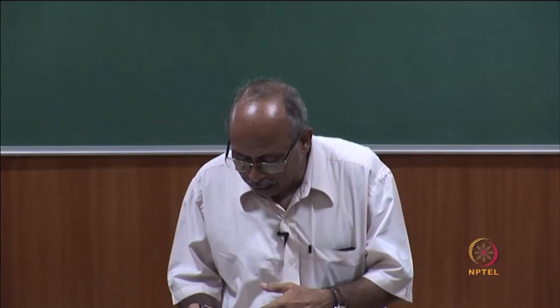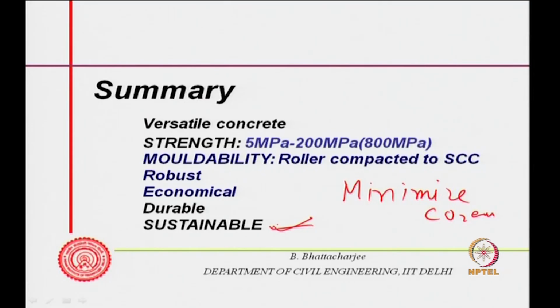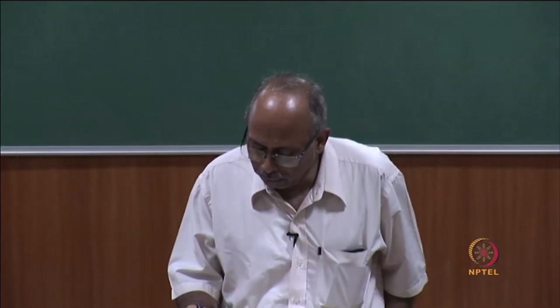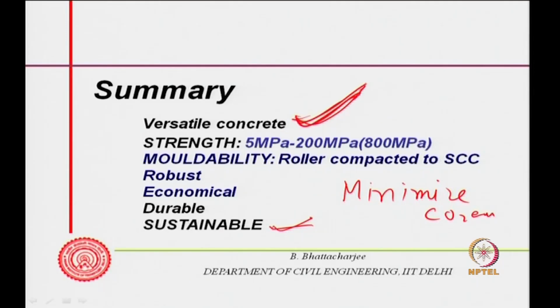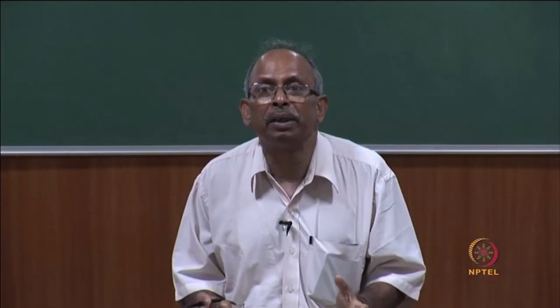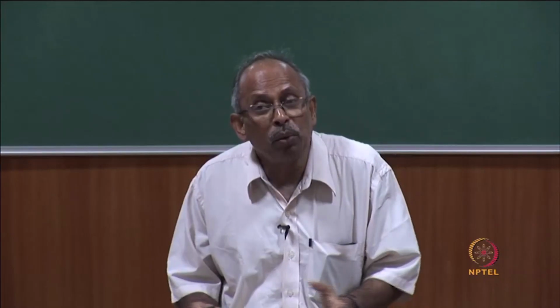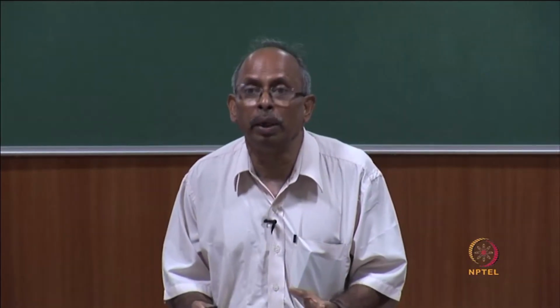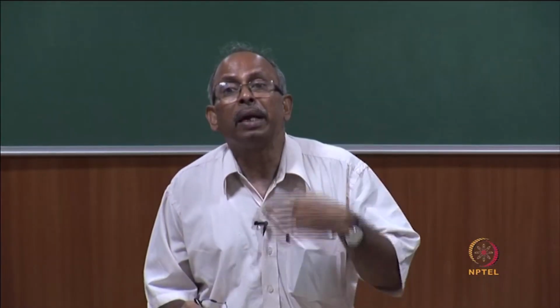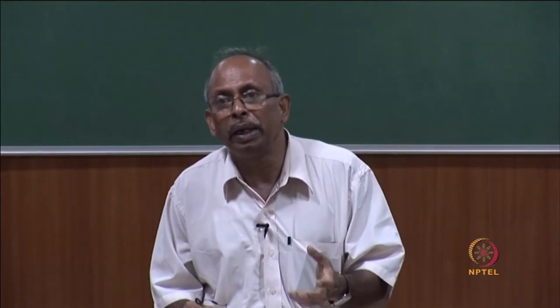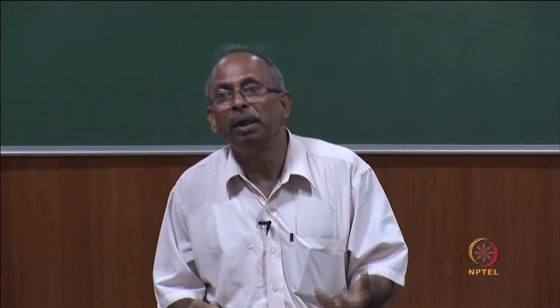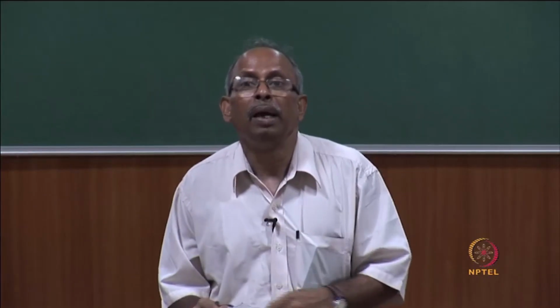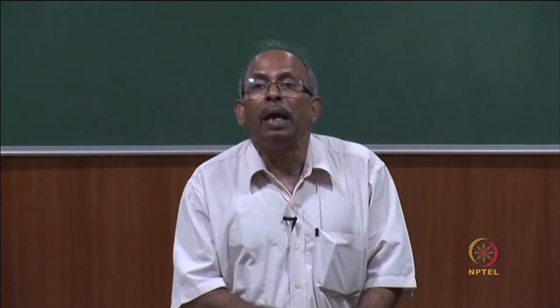So, this was the last one I looked into in the summarization, but first of all, through our 42 hours of discussion, what have we observed? Concrete is versatile. Where does the strength range from? 5 MPa to 200 MPa, maybe 800 MPa for cement based composites. So, it is really a very, very versatile material. You can design it for strength as you want. Put fiber into it, you can get the right kind of ductility that you desire, but if you do not, tensile strength improvement is not as much. You can obviously use reinforced concrete or pre-stressed concrete, but tensile strength also can be enhanced perhaps in future.